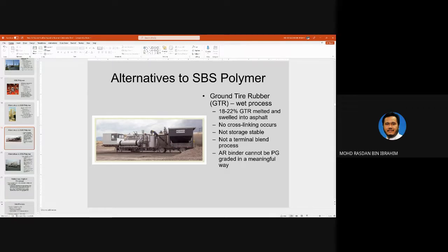Okay. So no cross-linking occurs. This is in normal rubber modified asphalt. No cross-linking, meaning that the rubber particles in the earlier stage will be suspended in the bitumen. But if you keep it there, it will settle to the bottom. So it is not storage stable. Typically, it is not a terminal blend process. Meaning that it is not storage stable.